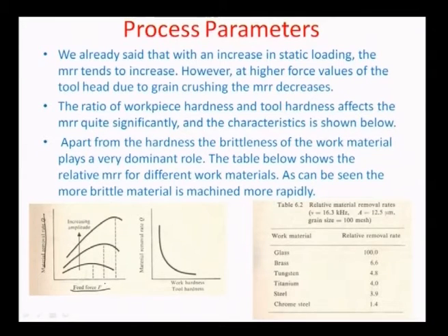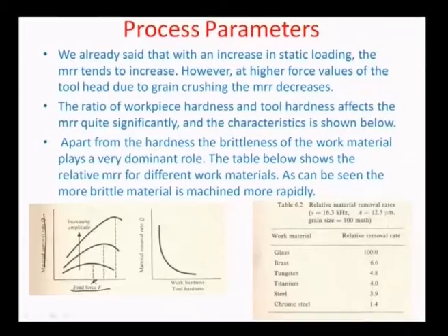So with an increasing amplitude, if the feed force is higher, for every feed force there is a crushing critical limit. For example, if the feed force is at a lower amplitude, meaning thereby that the overall gap between the tool surface and the workpiece surface is lower, then at a certain critical feed force value here, the grain crushing would happen, and this would keep on increasing. So the critical limit of the feed force goes on increasing, as you can see here, at which grain crushing begins. For example, at a lower amplitude it begins much earlier, and at a higher amplitude it begins later, and that is probably obvious because the gap in this case between the tool and the workpiece is more.